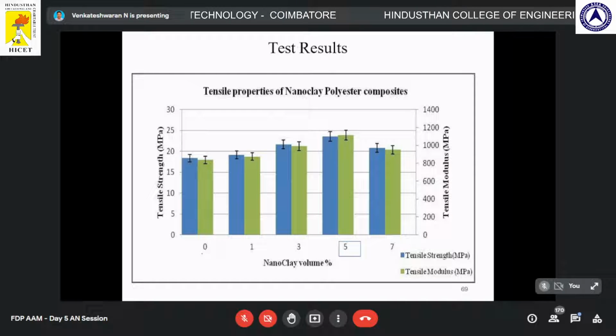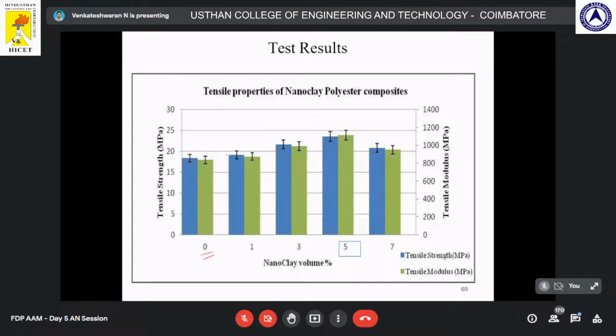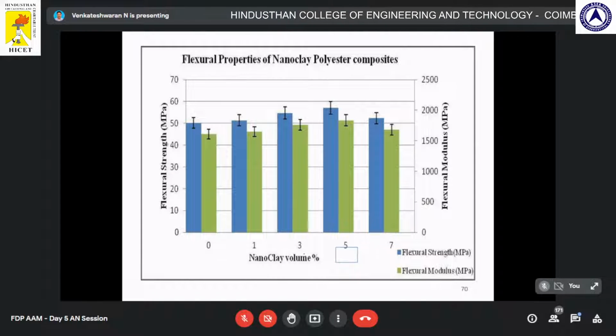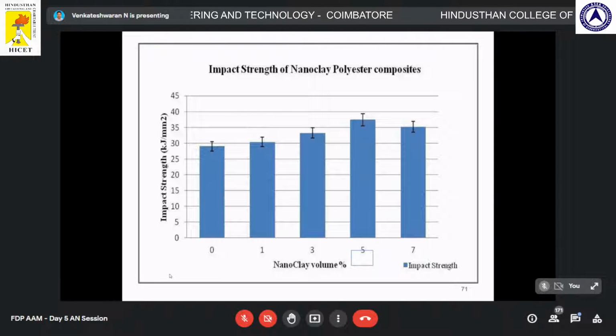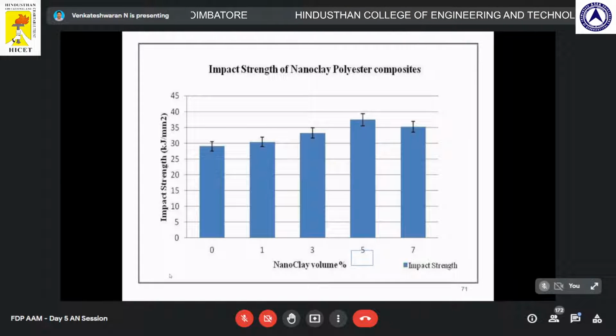So 0% is nothing but the polyester resin, and with the addition of 1%, a slight increase. Blue color indicates the tensile strength and green indicates tensile modulus. With the addition, it slowly increases and then starts to decrease at 7%. I get the maximum tensile strength at 5 volume percentage. Similarly for the flexural, it starts to increase slowly, reaches the maximum value and then decreases. Here also I am getting it at 5 volume percentage, and the impact response to failure is very high. So 5% provides the better tensile, flexural and impact properties.